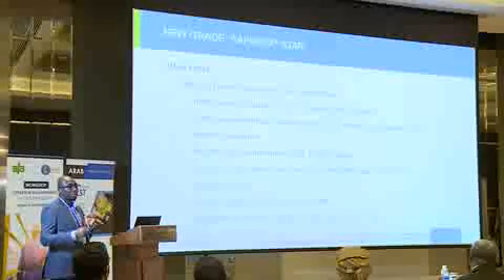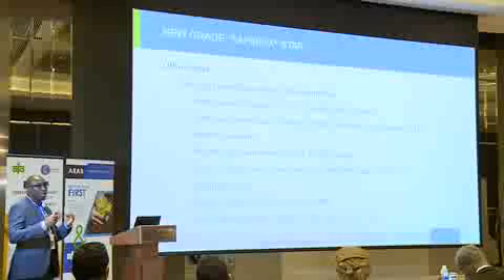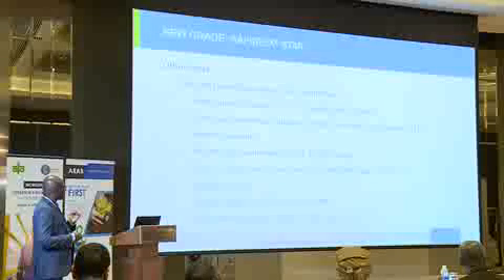To be able to fully accept this material as a heat exchanger tube material for Safurex for our strippers, we needed to carry out extra testing as well. So we did the strength of the tube-to-tube sheet weld. We had a block where the tubes were welded into this block as you would have in a tube sheet of a normal equipment, and then we carried out the pull-out tests. We also did the standard corrosion resistance tests that we specify in our Stamicarbon specification. So the Streicher tests were also done. We did some macro and microscopic examinations in the heat affected zone and in the weld.